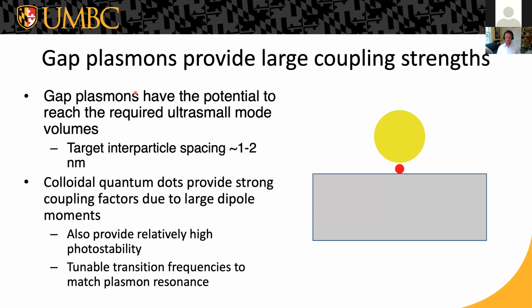So our goal is to make the mode volume as small as we possibly can. And I think it's been known, again, since the early days of plasmonics, since the surface enhanced spectroscopy days, that the smallest mode volumes, the greatest localization of light that you can get comes when you couple plasmons together. So if you take two metal nanoparticles and bring them close together, the plasmon oscillations in the two are going to couple electrostatically through the Coulomb interaction. Charge is going to be localized at the surfaces close to the gap between the particles, and the field is going to be localized in the gap much more strongly than it will be localized by a particle by itself.